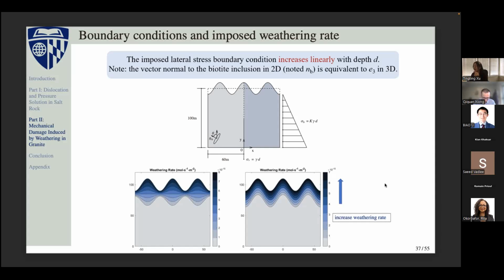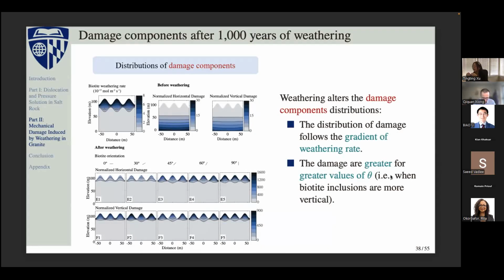With this study, the first observation is how the damage components, or how the microcracks, propagate under this condition with this biotite weathering pattern. Comparing the top figures, they give us the normalized damage component. You can understand it as the magnitude of the microcrack propagation. Before weathering, not much damage has accumulated, but after 1,000 years of weathering, you can see that damage has accumulated following the pattern of the biotite weathering. So under these simulation conditions, the biotite weathering is probably a controlling factor for the damage accumulation in this geometry.